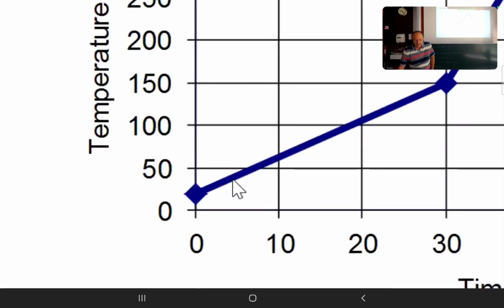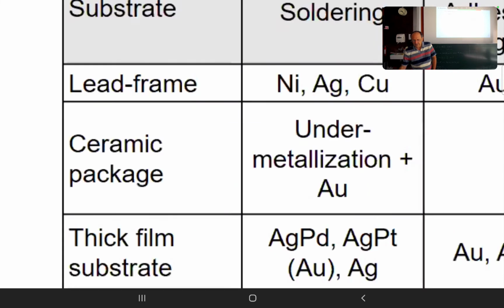Okay, again, we have here that typical profile: limited rate of heating, then faster heating, keeping it here in that case for 15 minutes in order to let the glass flow. It is wetting the parts, and then we cool down. Again, we see this within almost half an hour in order to avoid stresses that are too high.